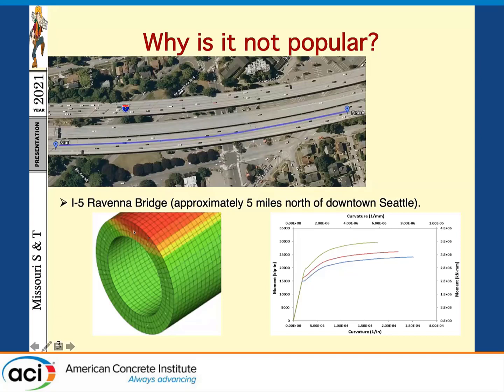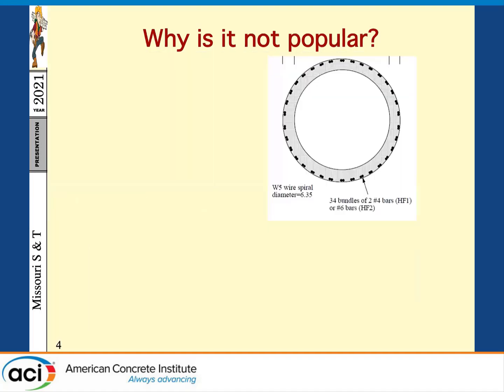This is the reinforcement over here. If you see the very tiny yellow dots over there, these are the reinforcements. So very easily we reach the unconfined ultimate strain for the concrete, the red area over there, and then you quickly lose those, which represent more than 50% of the area under compression. So this has led to rapid degradation in strength and hence relatively low ductility for the columns.